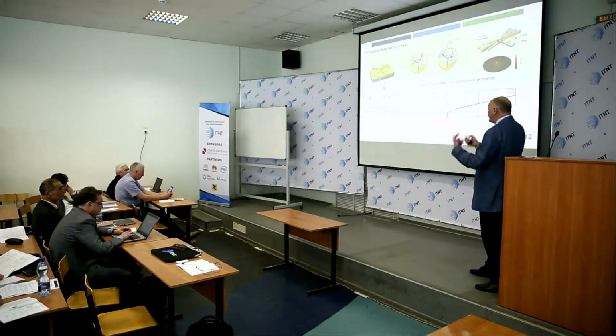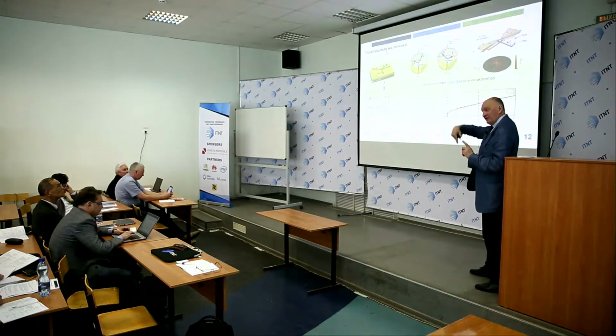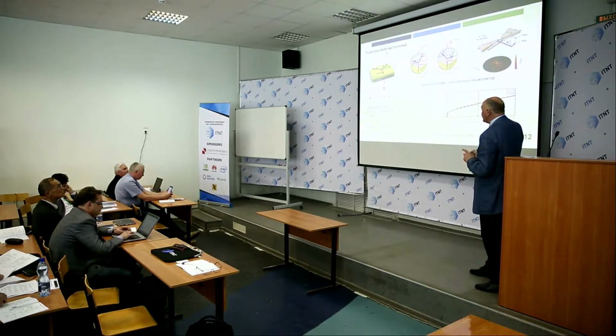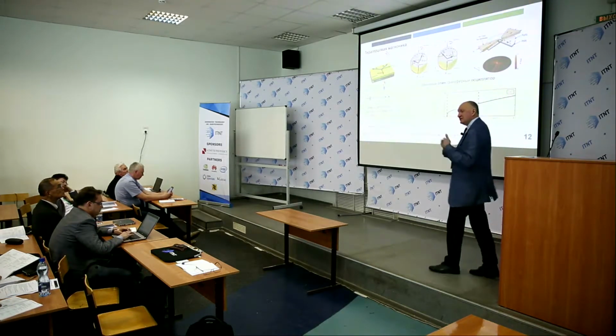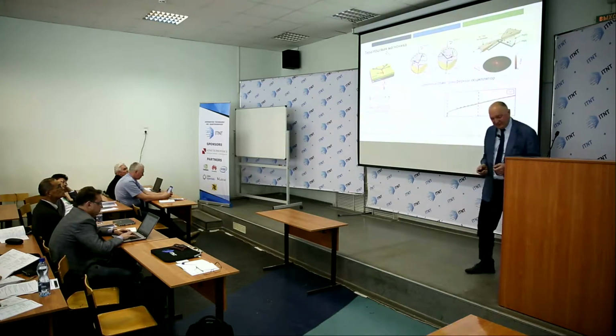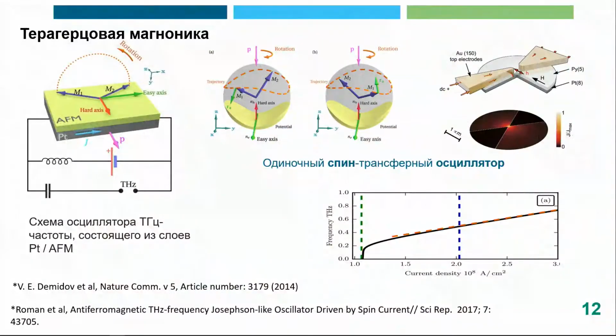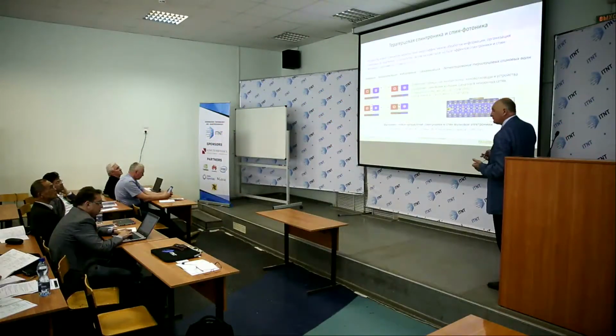which induces the interaction between two sublattices, and this interaction between two sublattices produces, by the inverse spin Hall effect again, a spin current in the platinum material, and this spin current is already in the terahertz frequency range. So this is a so-called spin transfer oscillator, and the frequency in this case was about 2 terahertz. However, it can also work with more terahertz.